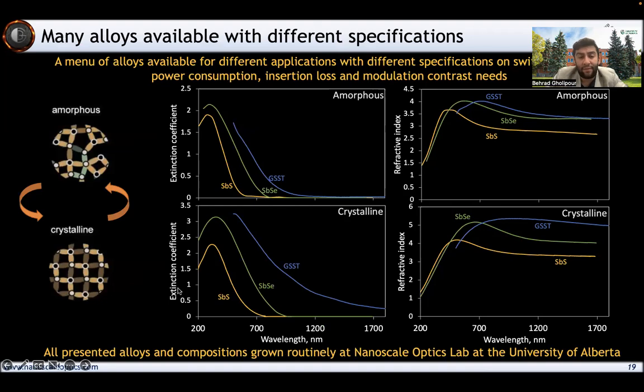So just showing you a couple of different alloys that are available and being widely used across many different industries and companies and academic groups these days. GSST, antimony selenide, SbS, these are some of the major alloys on the menu. Each of them have slightly different optical properties. So depending on your application, your wavelength of operation, you're going to choose the one that best suits you in terms of losses, in terms of the refractive index and the contrast that you need. And we make these, as I'm going to mention again, we make these routinely, all of these materials in our lab here at the University of Alberta.